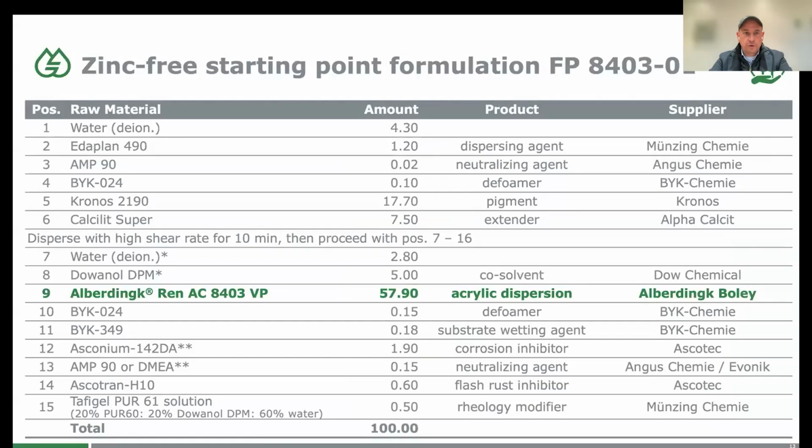We don't need to have the compromise of finding polymers which are so stable that you can have a good stability of the dispersion particle against bivalent cations, because there will always be soluble bivalent cations in such an active pigment, and they will potentially bridge particles. So you will see that in viscosity increase over time. You will see poor properties. You might see poor resistances of the dispersion film because people have deliberately stabilized the polymer so strongly that it can survive the bivalent cations.